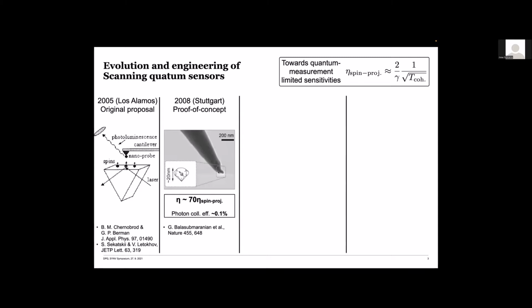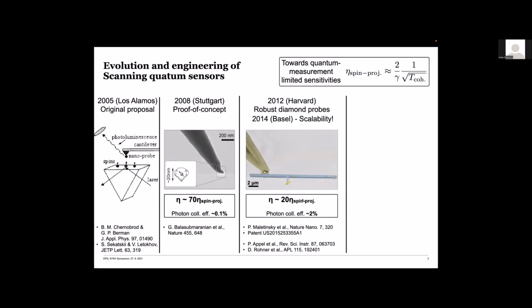And this was very nice for proof of concept, but really was still far from this optimal spin projection noise limited sensitivity by close to 2 orders of magnitude. So this is where I essentially started entering this field, when I was still a postdoc with Amir Yacoby, and when we introduced these scanning probes that you've already seen advertised several times, in particular also by Vincent. Here I just want to mention that next to these pillars being robust scanning probes, they're really photonic nanostructures. We engineer them such that they optimally guide this NV fluorescence to our detector and thereby improve sensitivity. And using this first generation of these tips, you see we improved here by roughly a factor of 3 or so.